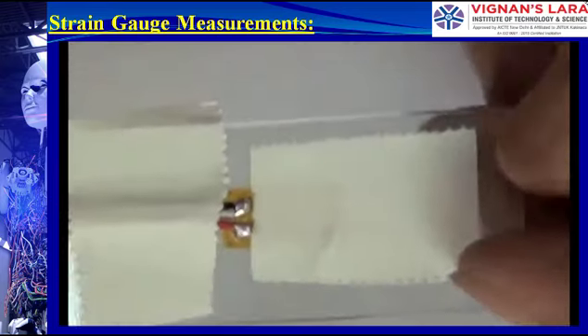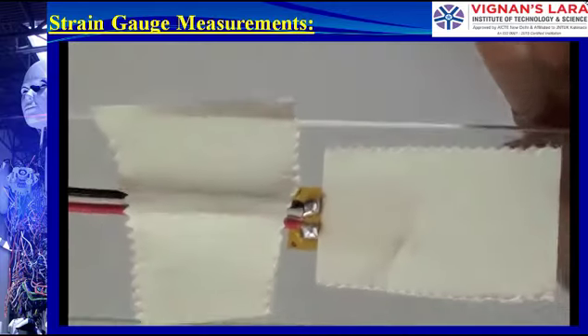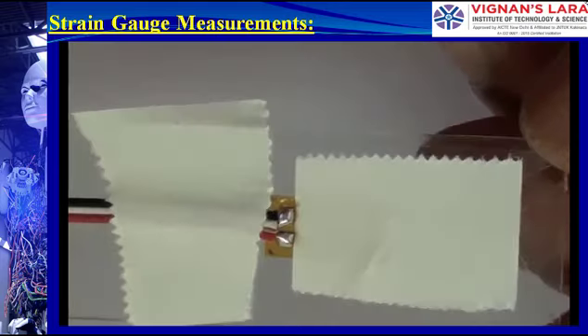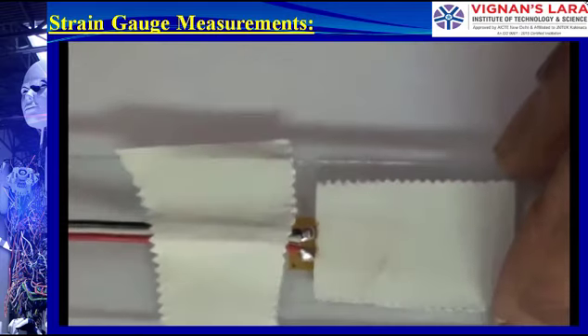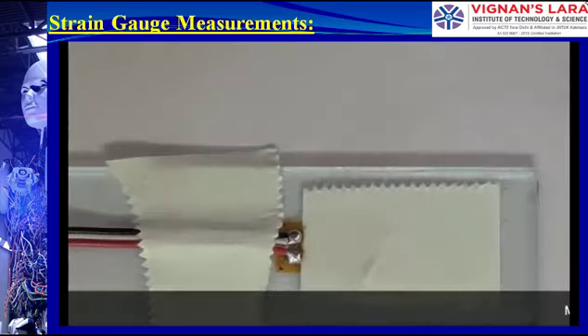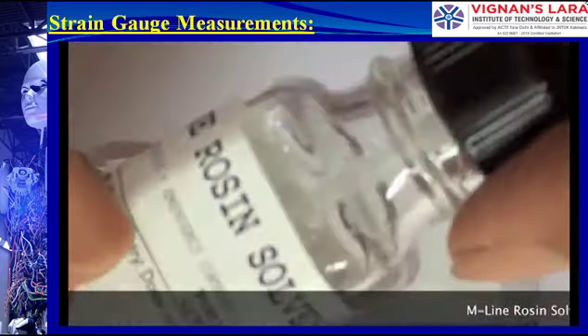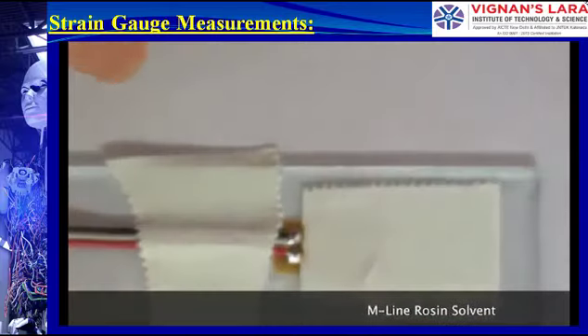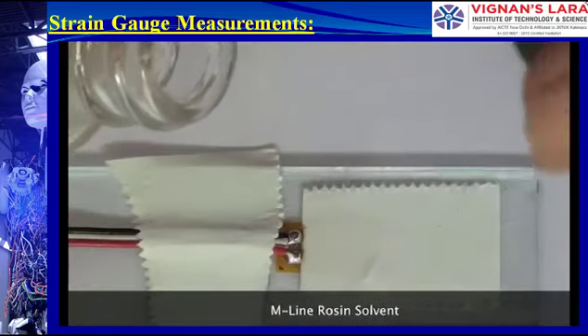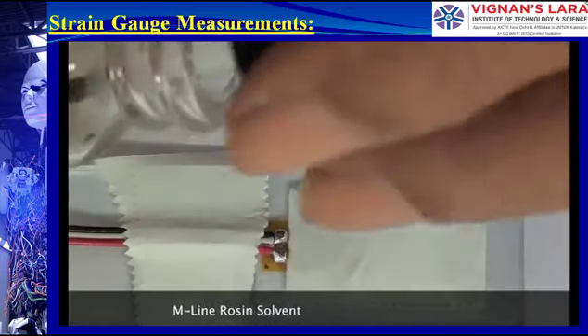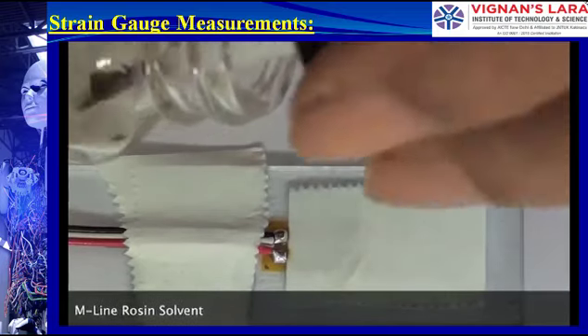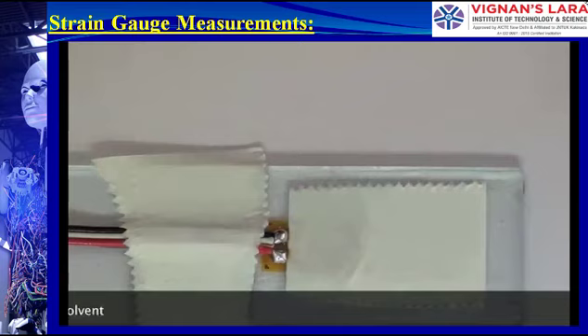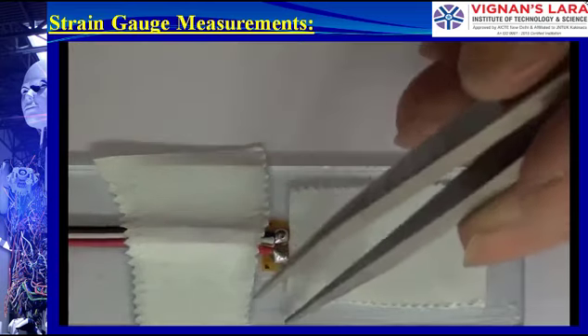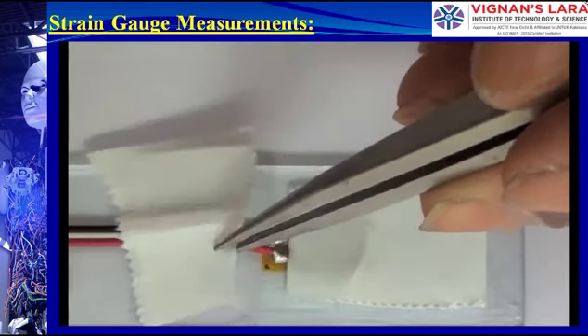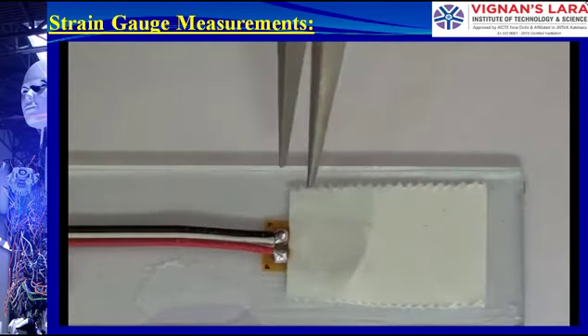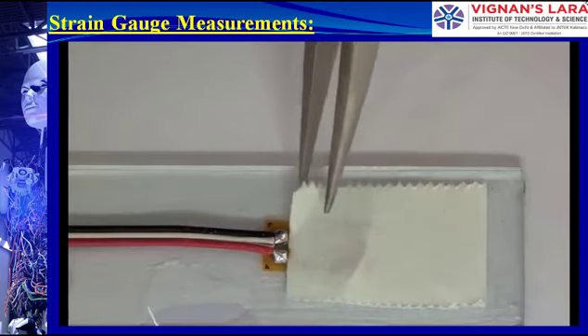The solder joints are inspected for proper connection, and if necessary they can be retouched with fresh solder. The PCT-2 tapes over the gauge and the wires are removed with a generous application of M-line rosin solvent, brushing the area a few times to dislodge the tape, which can be easily lifted away. The tapes should not be removed with any force to avoid damaging the soldered connections or the gauge.